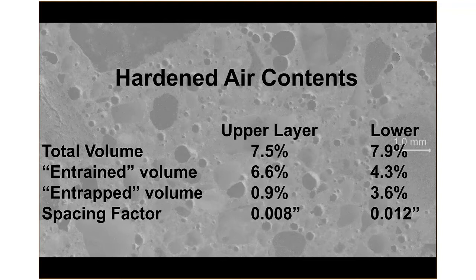Entrained volume, which are void spaces that are less than 1 millimeter or 0.04 inches in diameter, void spaces that are intersected when performing hardened air void content by ASTM C457, was 6.6%. The entrapped voids are again greater than 1 millimeter, and a sign of consolidation voids. The spacing factor, very interesting, 0.008 inches. This is right in line with the maximum that is required for freeze thaw resistance for modern pavements: 0.008 inches or less for spacing factor.